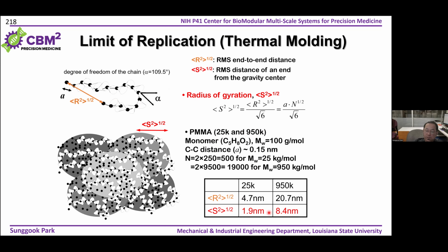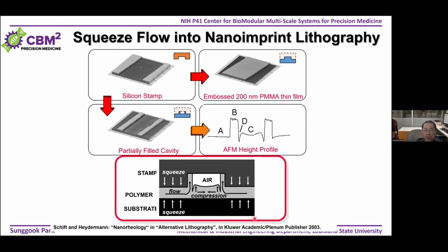What does it mean? This means the smallest feature size you can clearly differentiate with thermal molding is around 2 nanometers. But this is the case when we use 25K molecular weight polymers. If you use a low molecular weight material like UV resin, it can go further down, below 1 nanometer. So basically, there is no limitation in terms of the smallest feature you can produce using replication.